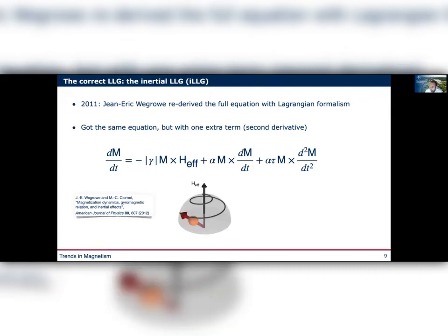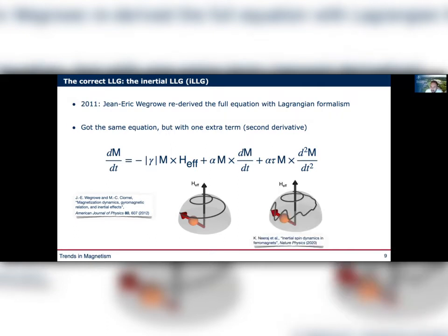What this term does is that the solution, instead of looking like the damped precession I showed before, now also includes a nutation on top of it. If you think of a spinning top, this is exactly what you would solve mechanically. This is what you would expect. In a 3D rotating object there is precession and nutation. The Earth has precession and nutation, so it has to be. It has to do with the conservation of angular momentum.